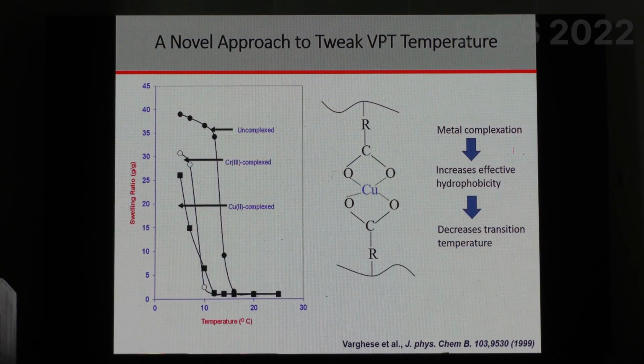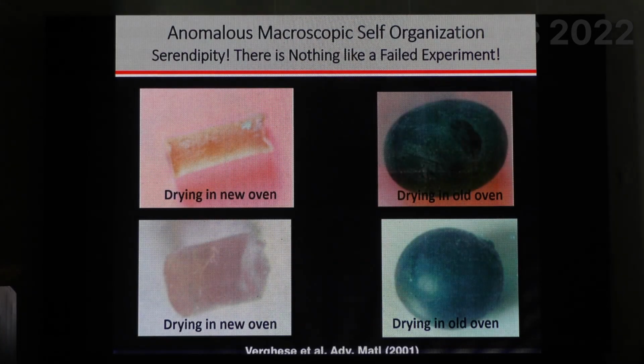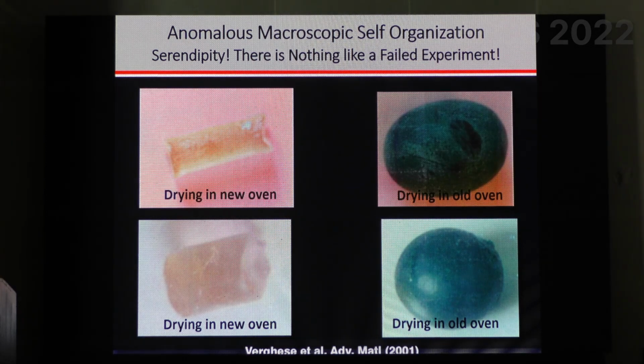Okay, and then we did lots of other things. If we put in a transition metal ion, the transition metal ion actually acts as a cross-linker, and it also changes the hydrophilicity, hydrophobicity balance, and therefore the transition temperatures. This is for students. I had my PhD student who did what we thought was a failed experiment. And it turned out to be, there's nothing like a failed experiment, by the way, okay? And this is a good example of it.